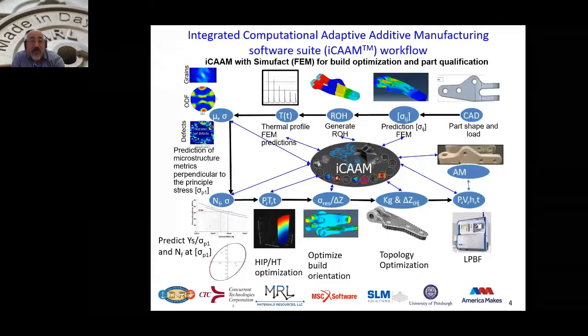So it starts from the top right corner when you get a CAD. Then we utilize our tools to identify, under in-service loading condition, the most critical area. And we identify what we call the region of homogeneity, which is simply we utilize some machine learning tools to identify the clustering within a large feature vector that includes the microstructure, the defects, as well as the external loading condition. Then we feed that at the most critical area, in this case the red area.